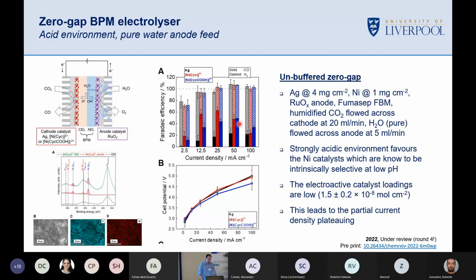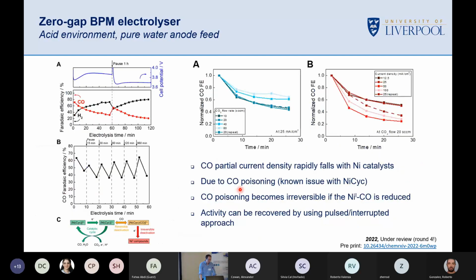The Faraday efficiency starts to drop though as we increase the current density. And that makes sense for a number of reasons. Primarily, it's the fact that we've only got a low electroactive loading. When you work out the number of catalysts present, and you work out the max turnover frequency, we're maxing out the catalysts quite literally. We just need more operational catalysts on the surface. So partial current density stays the same, Faraday efficiency drops as the total current density of the cell increases. Cell potentials are pretty rubbish, but we're not going to worry about those. I'll come back to that. So we're pretty pleased, but there's problems.